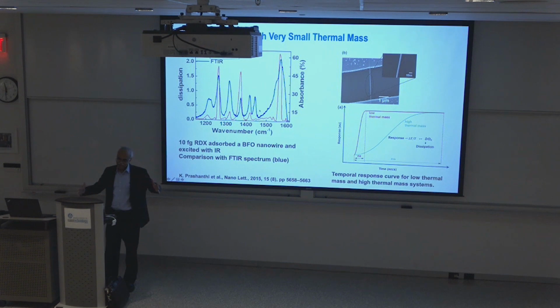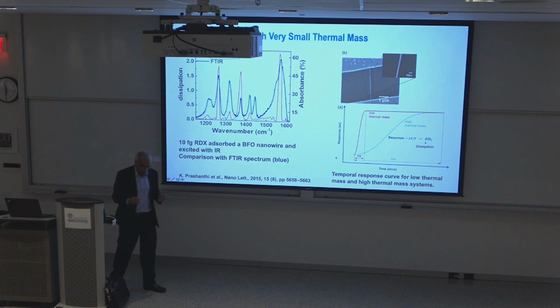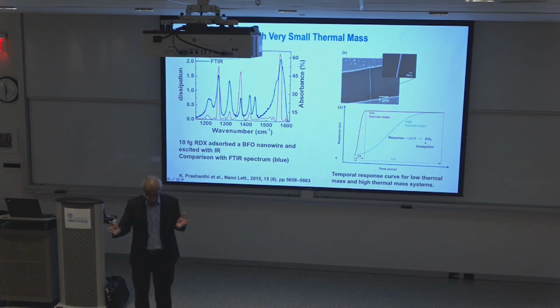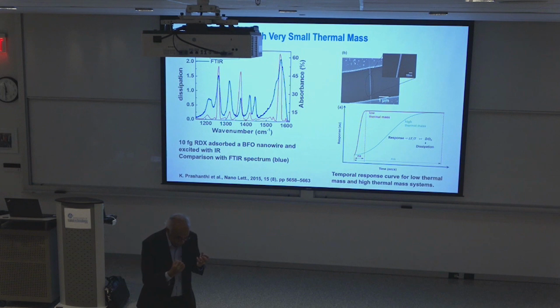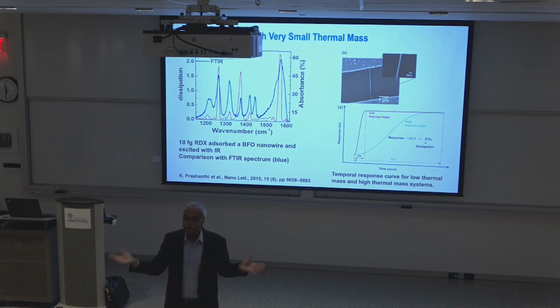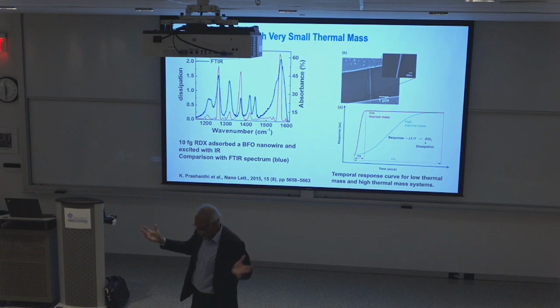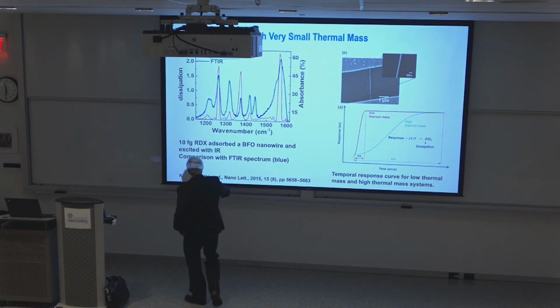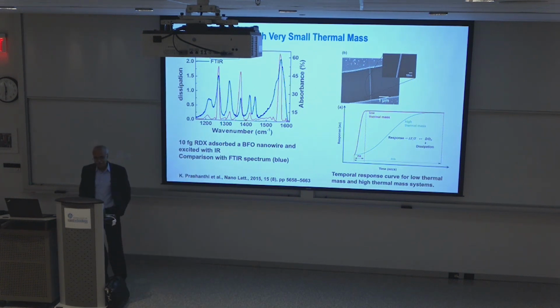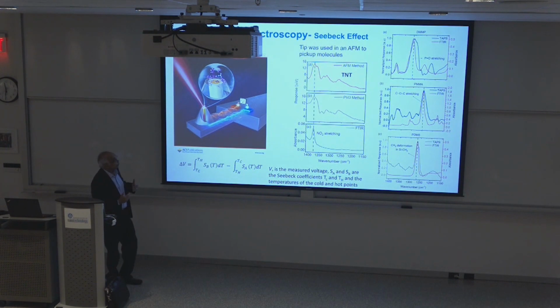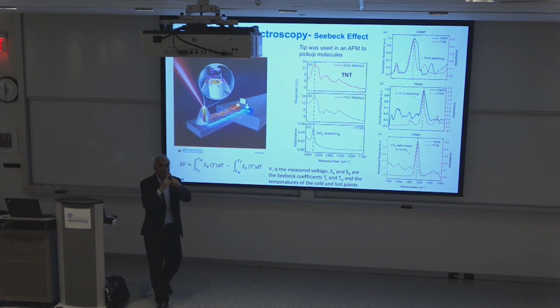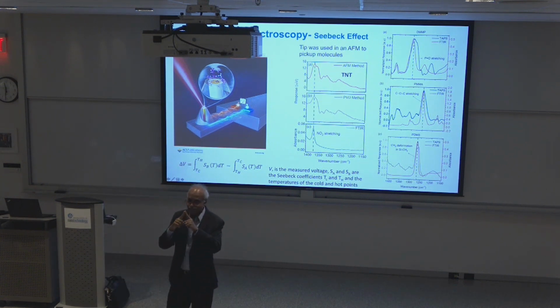Since we are doing calorimetry, measuring heat, the lower the thermal mass, the higher the response. So making it smaller makes it much better. We were able to get 10 femtograms of RDX absorbed on the surface. We can go even smaller. So this is actually a cantilever. It has two different metals that come up to the tip. At the tip, these two metals come together like a thermocouple, and the area where they meet is 25 nanometer radius.